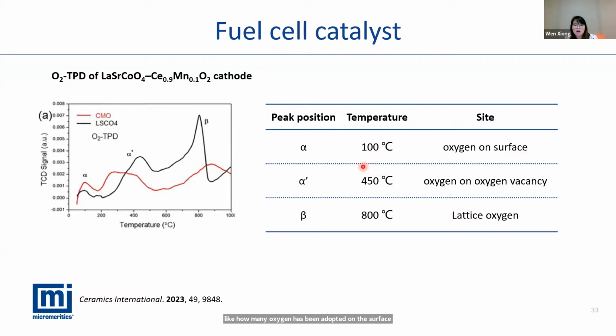For the peak at moderate temperature, around 450 degrees C, we can see that oxygen has been adsorbed on oxygen vacancies. By calculating the oxygen amount, we are able to see how many vacancies are in the sample. The third, high-temperature oxygen desorption means the oxygen has gone into the sample lattice, and it takes more energy, meaning higher temperature, to get that oxygen out of the sample.